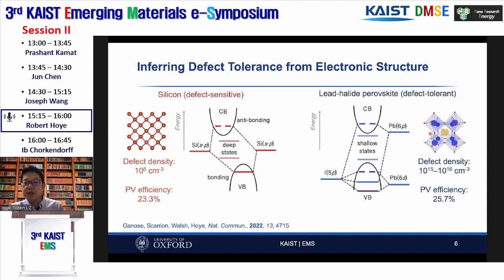The first approach is through chemical analogy, so substituting out lead for other divalent cations like tin or germanium. The second approach has been to find structural analogs like double perovskites, other materials with a perovskite crystal structure. But the third approach, and the approach that we've been taking most, is to find electronic analogs. So not necessarily perovskite compounds, but materials that can replicate this particular electronic structure, which based off this model is important for achieving defect tolerance.